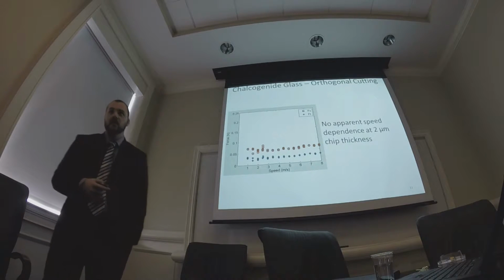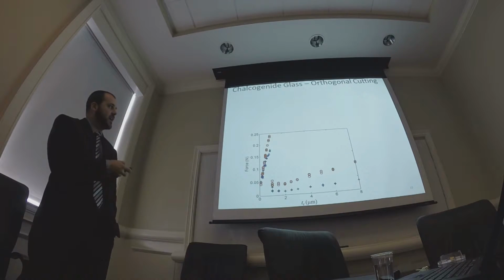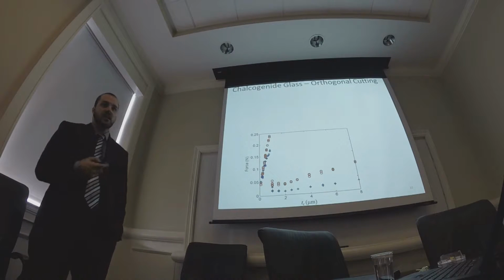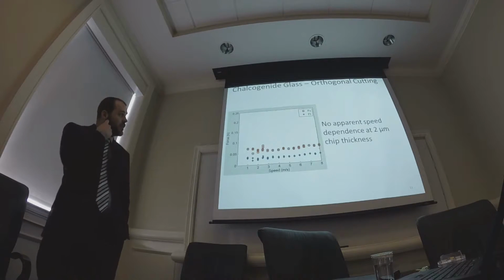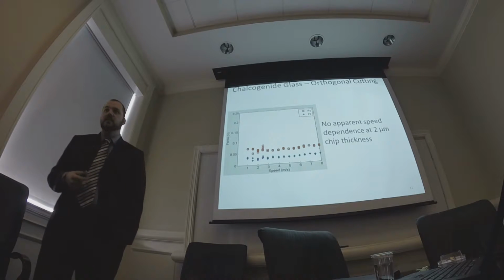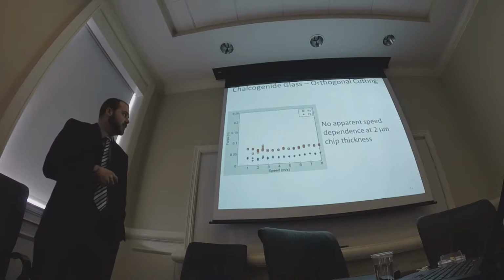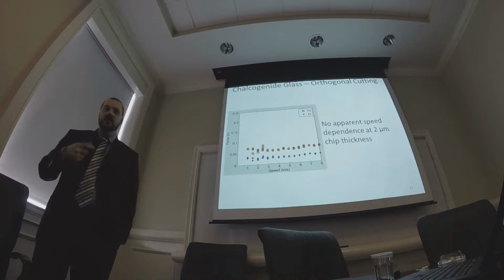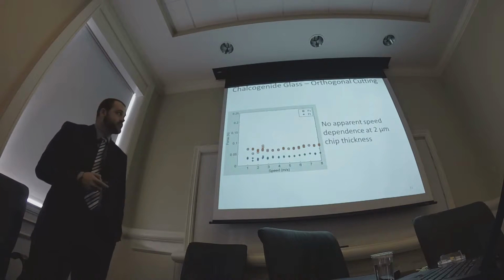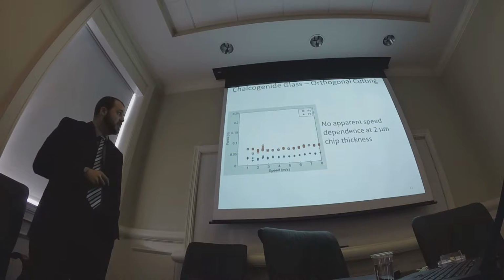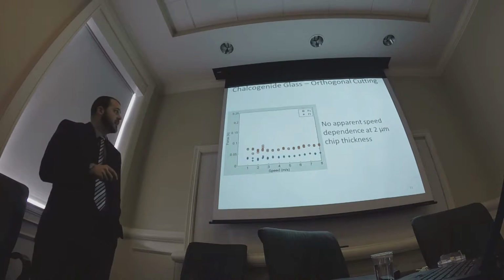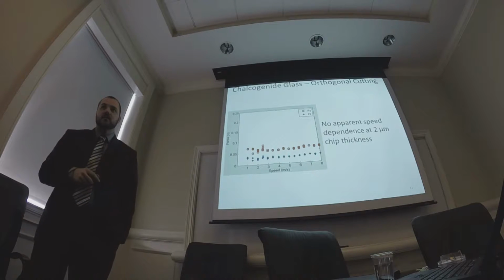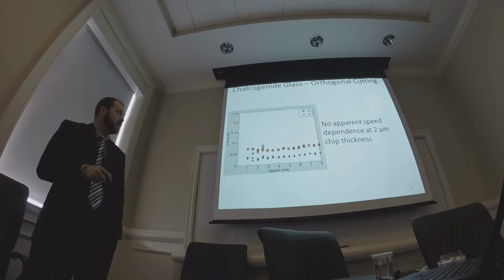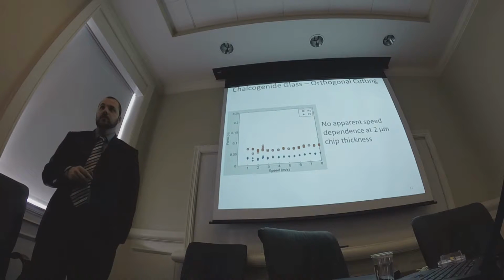So the next thing we wanted to look at was - we now know we've got a change in cutting force coefficient relative to chip thickness. Now we want to see is there a speed dependence? Are we seeing at different RPMs, at different cutting speeds, a change in force? At the range I'm showing here from 1 to 8 meters per second at a constant chip thickness, constant chip width, we're not seeing any noticeable change with speed.